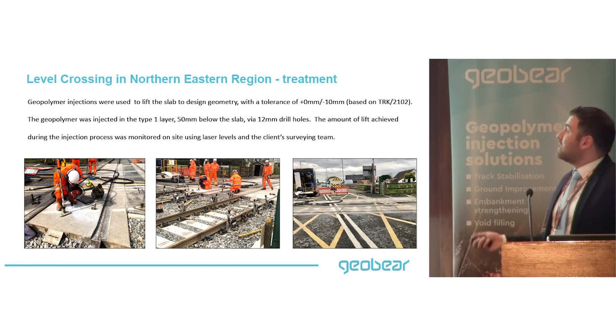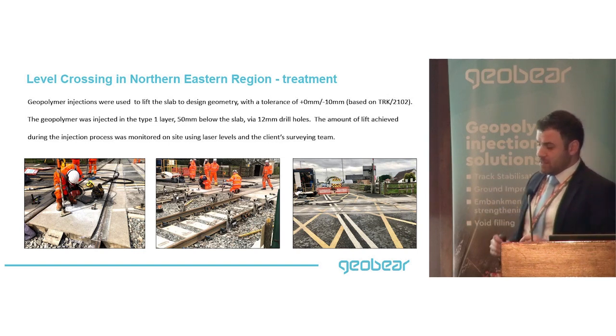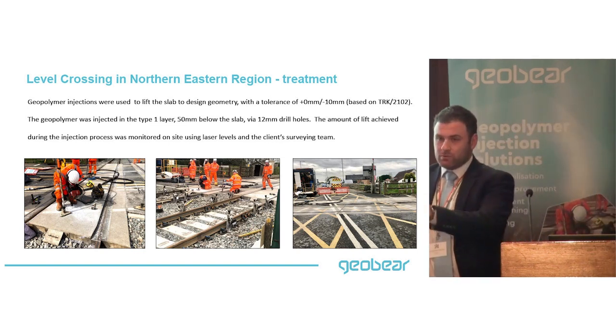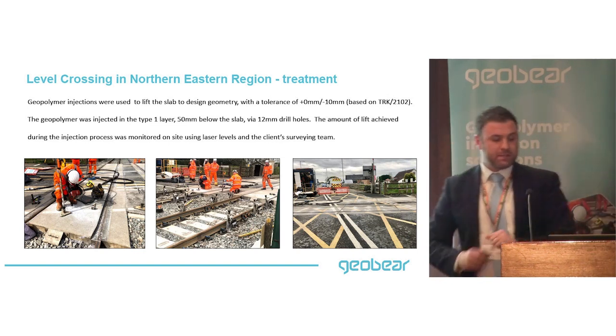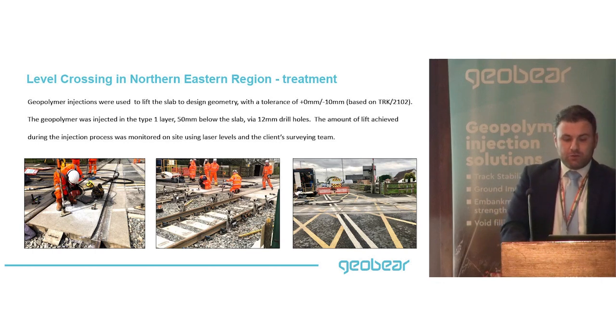And what we've done, we basically carried out the injections 50 mil into the subbase. So we drilled through the slab at multiple locations, went 50 mil within the subbase, and injected the geopolymer.